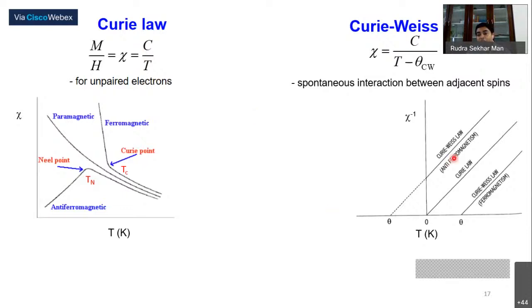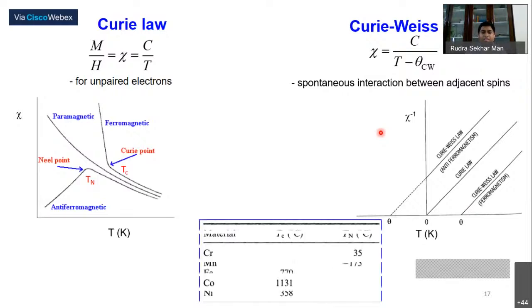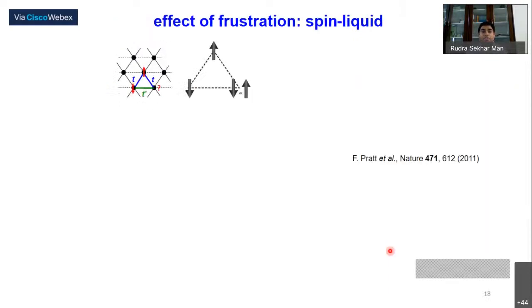But in the case of a ferromagnet or antiferromagnet, you have to take the interactions into account. Above some temperature, because of thermal fluctuations, you don't see any order. But if you cool it down, you see order, and in a ferromagnet you call it the Curie temperature, and in an antiferromagnet, the Néel temperature. That is how you define the Curie-Weiss temperature in this plot. This is very easy to visualize. The Curie-Weiss temperature is positive for a ferromagnet and negative for an antiferromagnet. So if you do a measurement on a sample, you know what type of magnet you are dealing with. There are typical examples of ferromagnets and antiferromagnets, with Tc and Tn for different substances: chromium, manganese, iron, cobalt, and nickel. These are the elementary magnets.